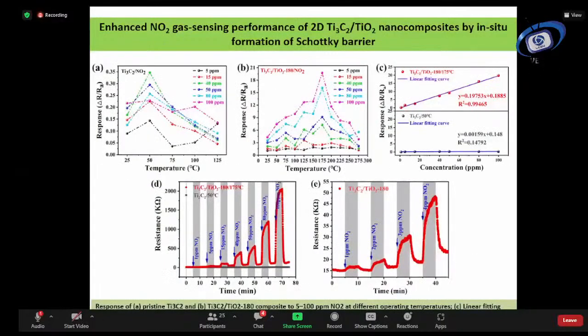And these are typical curves, just supporting data, for different concentrations tested at different temperatures and different parameters, and a linear response has been seen. It also shows a maximum linear response of 0.9, and that is more than ideal.